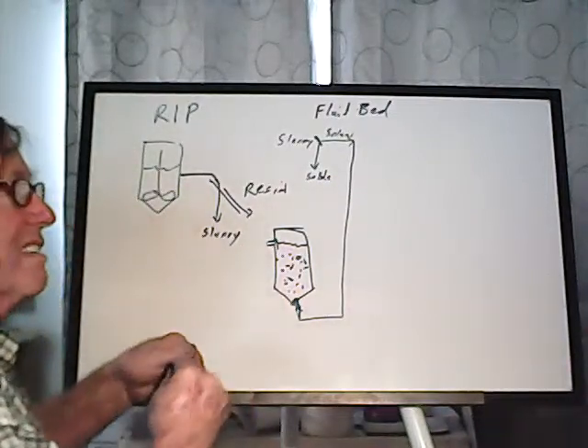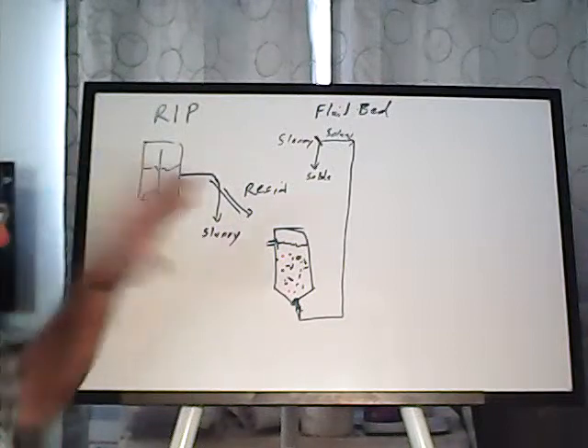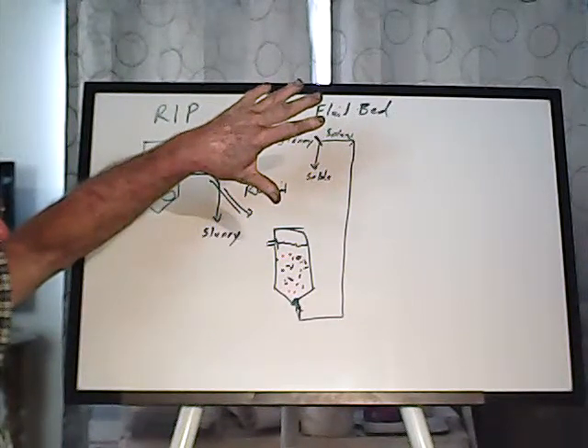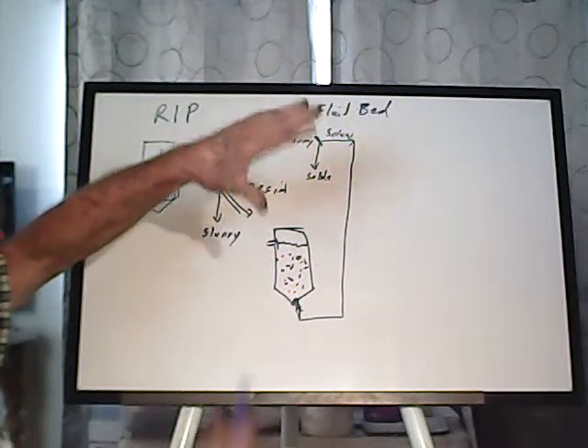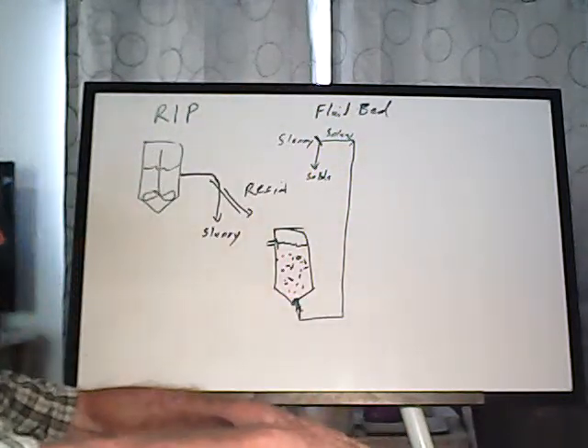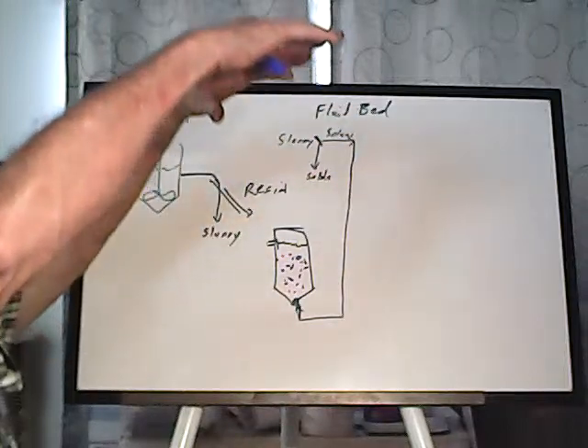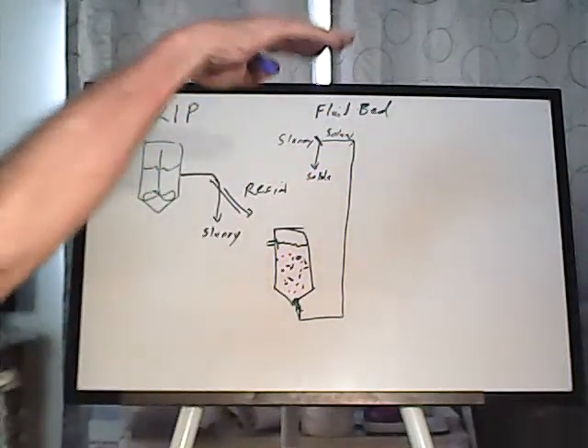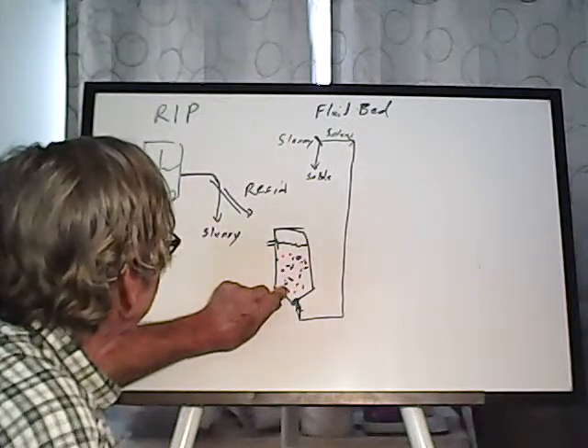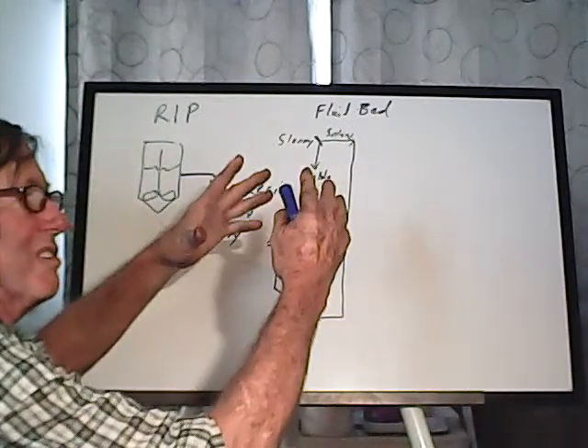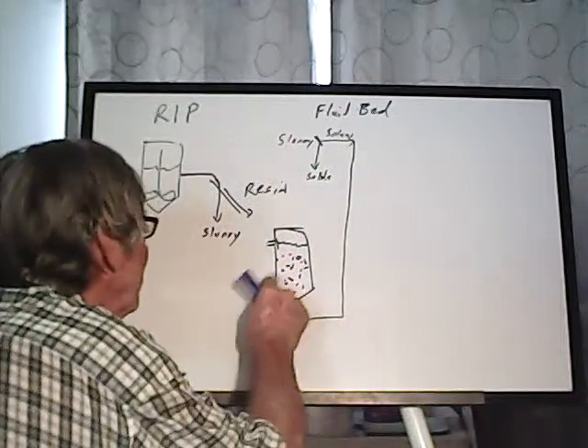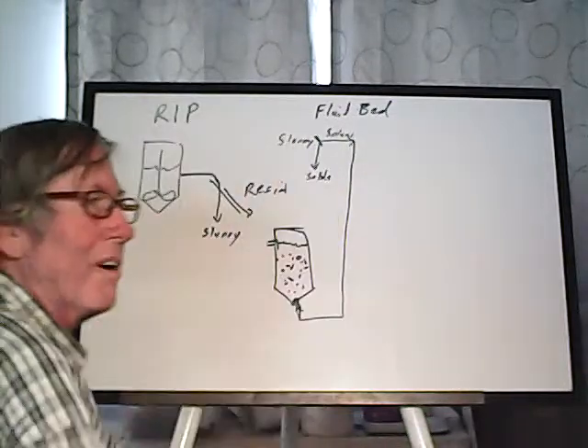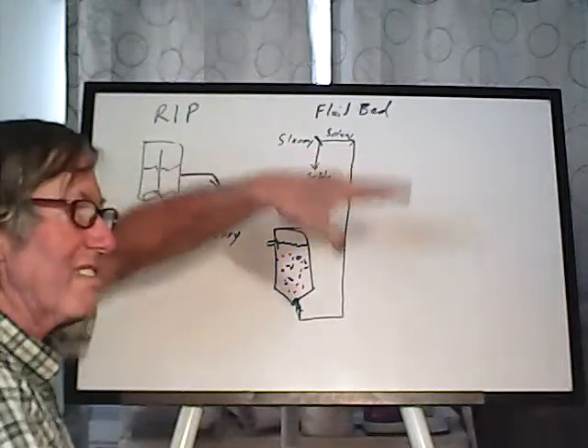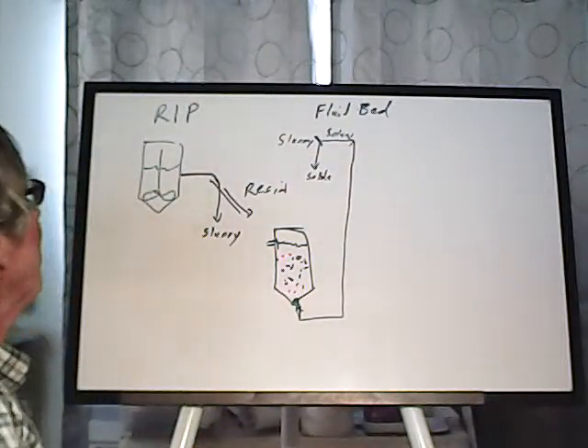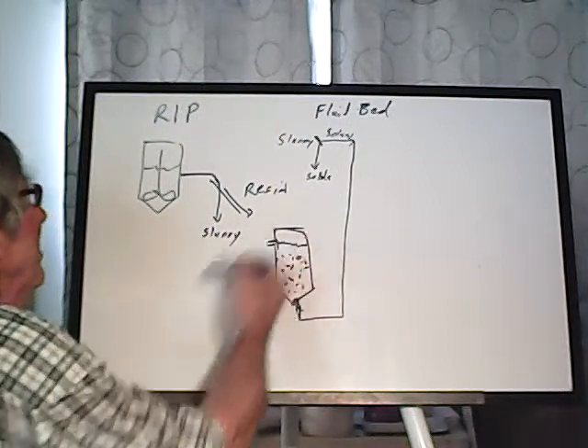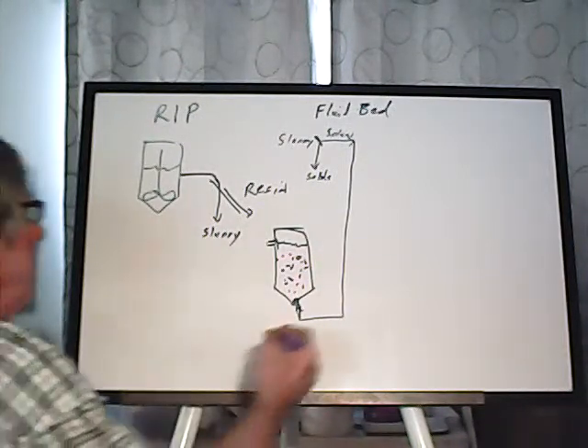It's interesting to watch when you're using a fiberglass or HDPE, one of those kind of clear tanks. You can actually see the bed go. And then it creates a fairly stable surface on top, because the space between them, once you inflate it to a certain amount, then the solution can get through there without exerting any more pressure, and it creates a fairly flat surface. It's really quite interesting.